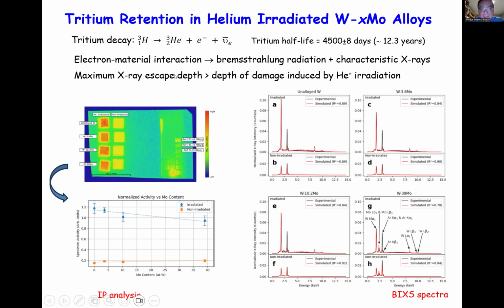The maximum X-ray escape depth corresponds to the depth of damage induced by helium irradiation. So in other words, we can use this to actually understand where the tritium is in the microstructure. The first thing you can do is put an image plate, and then you can see for those materials, and the ones which were not pre-implanted with helium, the difference in the activity, the radioactivity that you see. So if you have helium and damage, it makes things worse, or it retains more tritium as compared to isolating the effects independently. And then we can also measure the energy profile and simulate that.